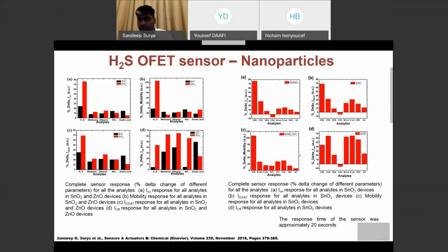So there also, what we have identified is, sorry, tin oxide based OFET is highly selective towards H2S gas alone as compared to other materials in this case, like you can see. Another good advantage of this OFET that I have developed is its response time was very quick. It was responding within 20 seconds to reach the highest 90% maximum of the transient curve.